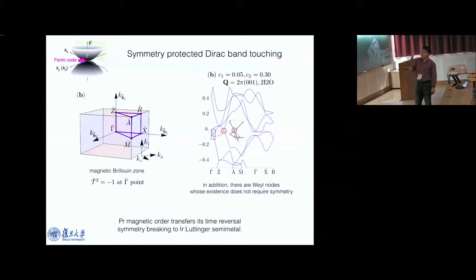In addition to these symmetry protected nodes, there are also a bunch of Weyl nodes near the Fermi level. The reason you have these Weyl nodes is because this quadratic band touching Luttinger semimetal is the mother state of many topological phases. If you break time reversal, you can automatically generate these Weyl nodes. If you get a band inversion, you get a 3-dimensional topological insulator. Yeah, so this Luttinger semimetal is the mother state of many interesting things.